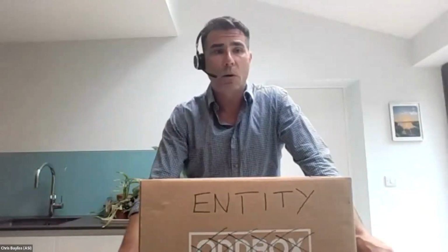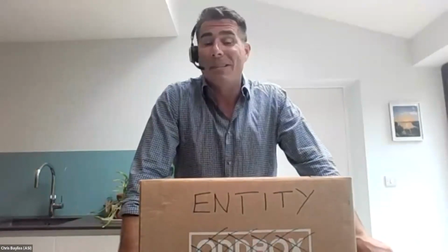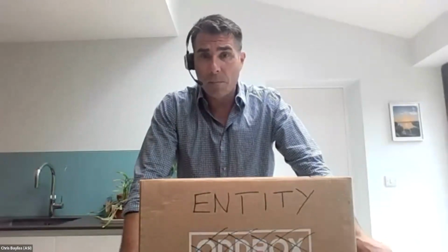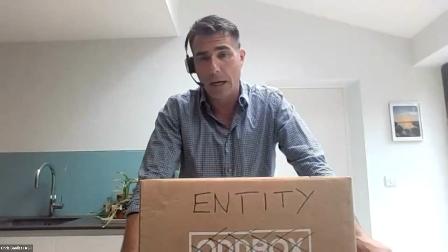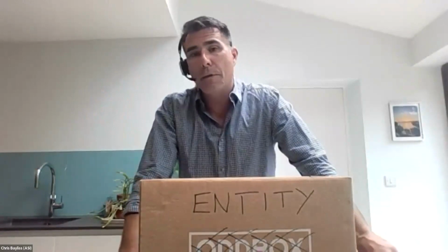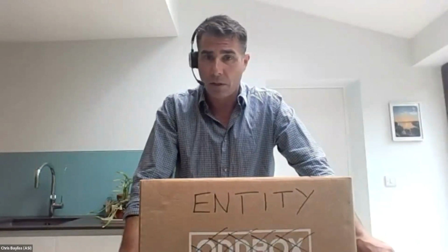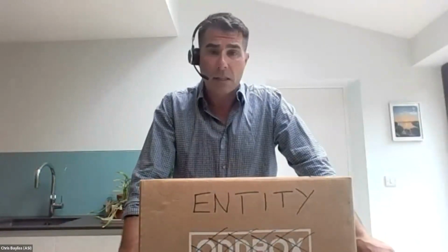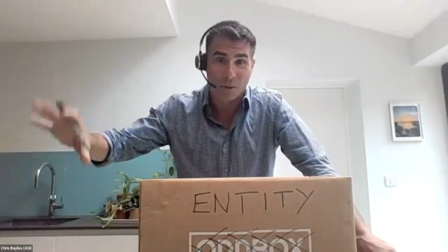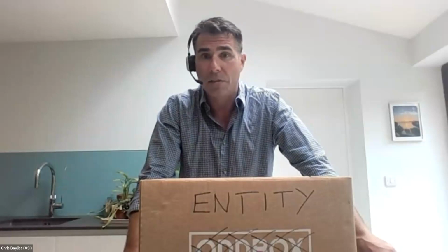Let's say you have a can manufacturer with a yield of, I don't know what the numbers are, but I'm going to say 80%. So they're consuming 100 tons of rolled material. They produce 80 tons of cans and 20 tons of scrap, just as an example. And let's say their input to that can manufacturer is 50% chain of custody certified. So ultimately 40 tons of their output of cans, 50% of the total 80, is ASI Aluminium, is chain of custody certified.